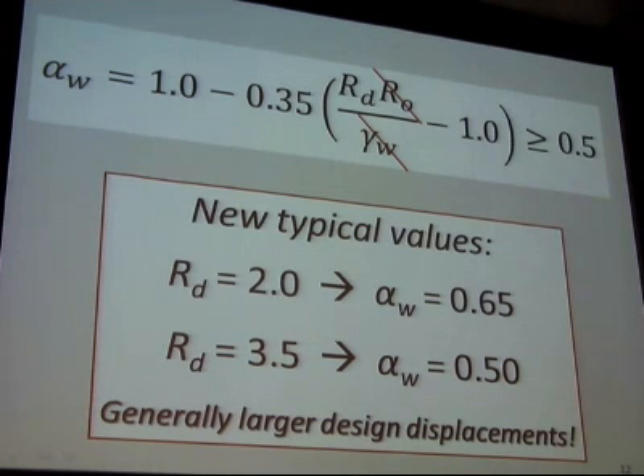So if you've got a moderately ductile wall with an RD of 2, we're talking about 0.65, so that's a reduction from 0.7. And if you've got an RD of 3.5, we're down to 0.5. So very important, this new expression means generally you have lower effective rigidities of shear walls and therefore larger displacements. And indeed, even our seismicity is going up here on the west coast, so our displacements are going up.